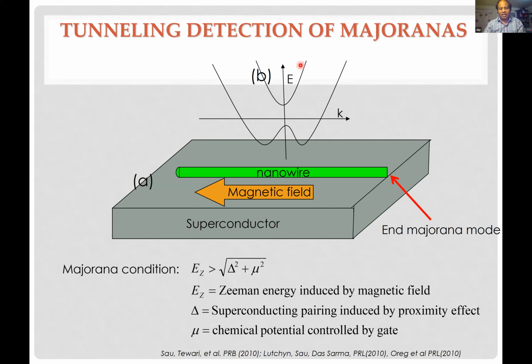In this picture, the magnetic field B would be above B critical. So indeed, we come up with this condition: the Zeeman splitting from the magnetic field was beyond this critical value. So really what's important is the Zeeman splitting from the magnetic field, not the magnetic field itself. And this depends on the so-called gyromagnetic ratio, which can be different in a semiconductor from 2.